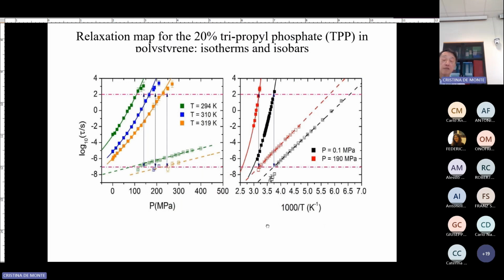So there are more experiments, different representation. Again, I wouldn't go into detail, but you can see from here, whenever you change pressure and temperature, you change temperature only, and you see that the alpha beta remain the same whenever at Tg, which is a fixed 100 seconds, the same place. They are all the same. You can vary now different pressure, and then again same thing, they remain. This is a different representation, but shows how general it is.